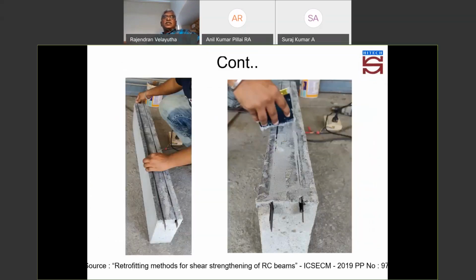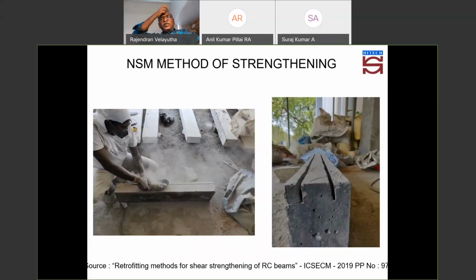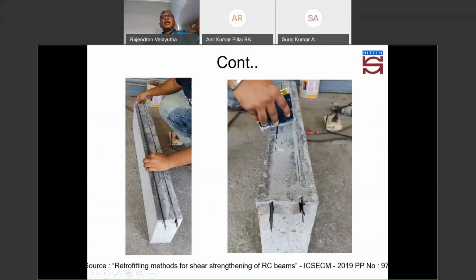As far as the CFRP strips are concerned, you have two systems. One, you can go with near surface mounting, or you can simply stick the fiber sheet or strip onto the concrete surface. It is always better to go with an NSM because it acts as part and parcel of the concrete member, where you make a sleeve, insert the carbon strip into that, and then finish off with an epoxy glue.